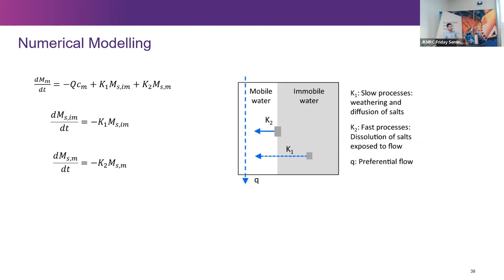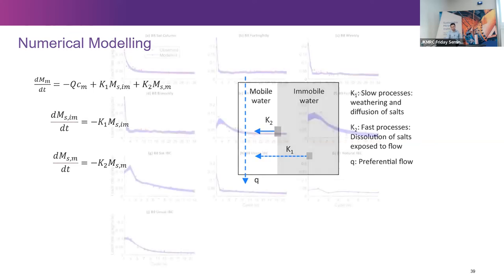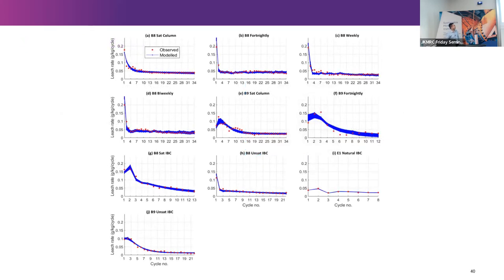And then the modeling is based on the change of mass over time and as a function of flow rate and the slow and fast processes. This is what we used to model, and my supervisor Neil McIntyre had calibrated these models and found a good match with our experimental data and the numerical models that he developed. He also used rainfall data and extrapolated this, but we haven't validated this yet, and there is some degree of uncertainty, but there's still some predictive capacity to be able to extrapolate this to field conditions.